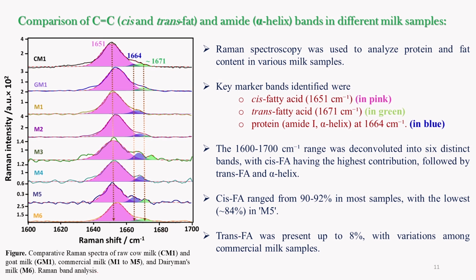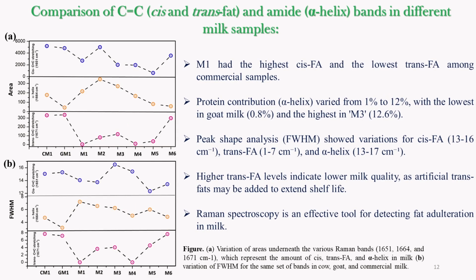But in many commercially available milk, trans fatty acid is low, but it is seen that it can go even up to 8%, which is more than what we expect. So this analysis helps us to talk about whether the commercially available milk is good or bad, or we can also talk comparatively, whether this company is better than that, considering the presence of cis and trans fatty acid. So we have done some more band analysis of the cis trans band. This is how the FWHM is changing, and how the area is changing.